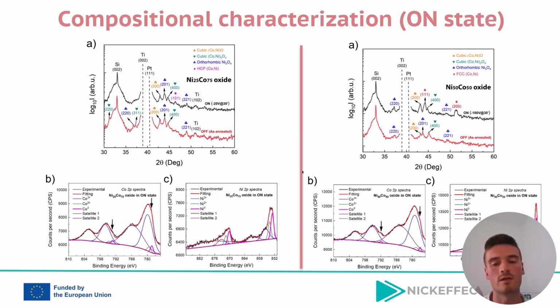So when studying the underlying events, X-ray diffraction and X-ray photoelectron spectroscopy characterization reveal the suppression of some peaks related to the mixed cobalt nickel oxide when switching from the off state to the on ferromagnetic state.